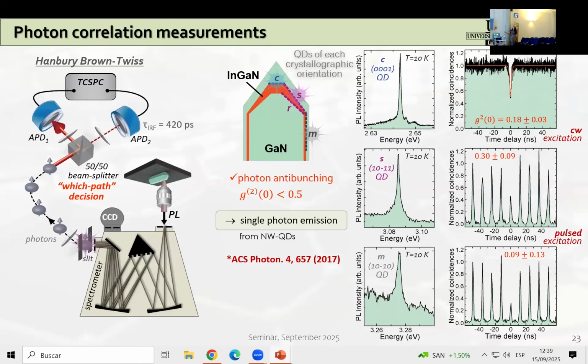system, then the G2 values at 0 time delay, as you can see written here, go well below the 0.5 threshold in the case of two independent quantum emitters. And this is a clear signature of single photon emission from nanowire quantum dots.